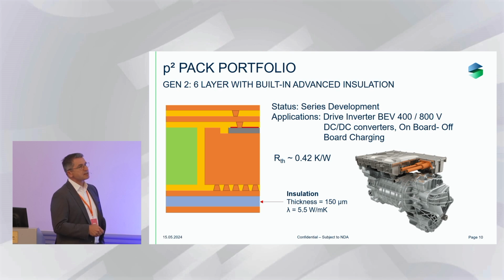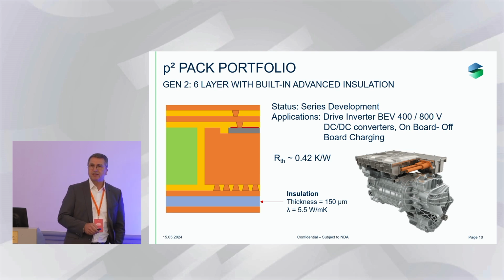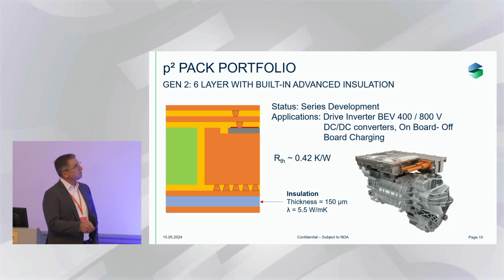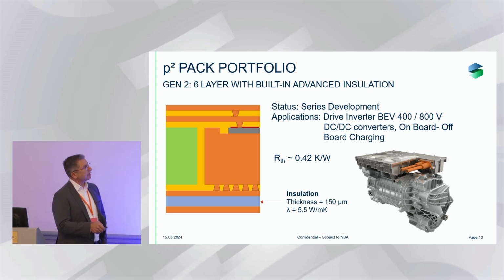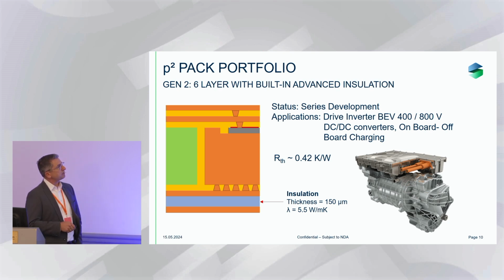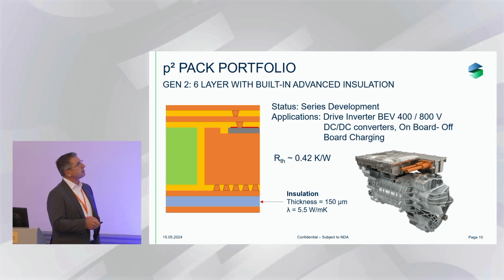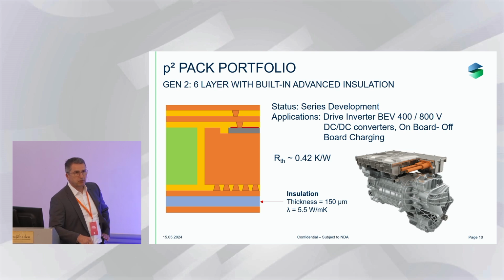The thermal resistance is jumping up to more than double of this value, even though we are using materials which are heavily filled with ceramic material, so the thermal conductivity is 5.5 watt per meter Kelvin. Still, with this thermal resistance, you can achieve very nice module resistances. One of our customers had 4 devices in parallel, and the module resistance was 0.1 Kelvin per watt.